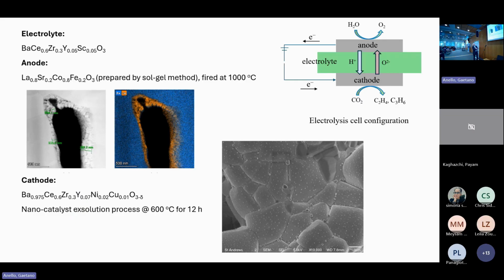Here we have one alternative for the anode. So we've got lanthanum strontium cobalt ferrite coating, a perovskite. You can see it's a nice coating. And then here's a copper exsolution from a typical barium cerium zirconate. So these are our nanoparticles that we can take forward. And the next stages are to go and produce some olefins or produce something.